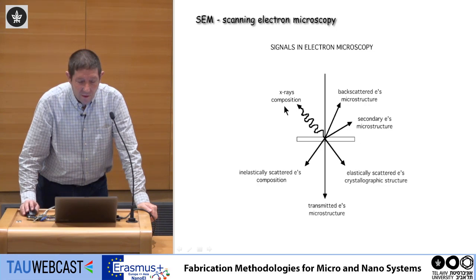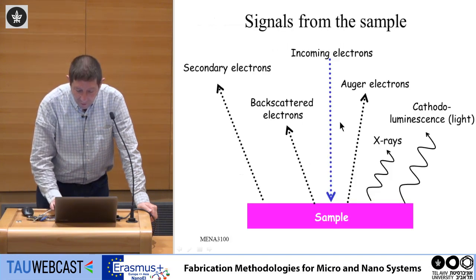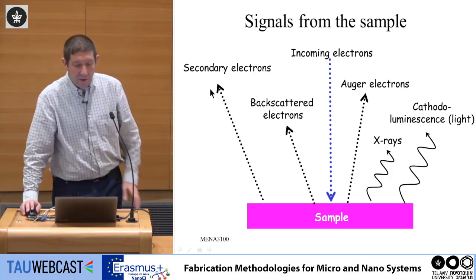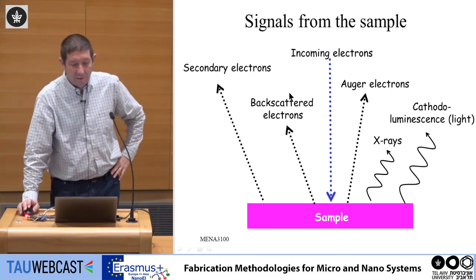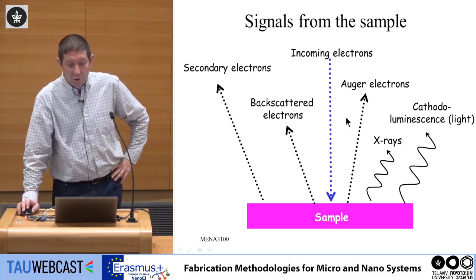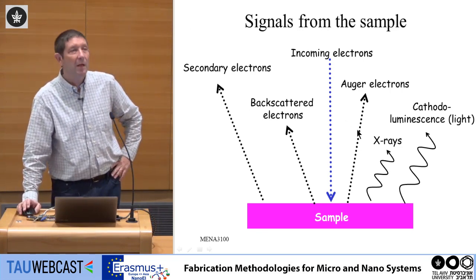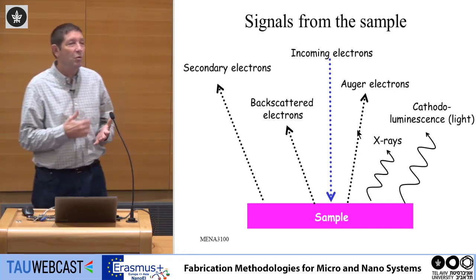So in a SEM, you look at the signal above the sample. In TEM, you have the transmitted electrons, and inelastically scattered electrons for composition. So in a TEM, you look at the electrons going through the sample. In a scanning electron microscope, you look at electrons coming off above the sample. And you can have secondary electrons, backscattered electrons, Auger electrons, which are electrons emitted due to Auger interaction.